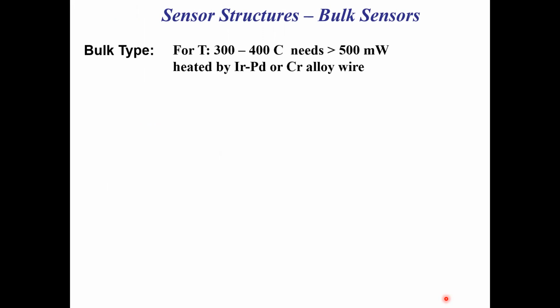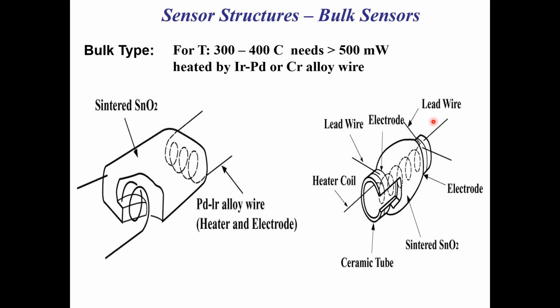So if you make a bulk type sensor, which you can, it requires a lot of power. If you want to take a bulk type sensor and heat it up to 300 or 400 degrees C, where the sensors are active, you need large power, heated by iridium, palladium, or chromium alloy type wire. You can see the bulk type design of sintered tin dioxide sensor heated with palladium iridium wire, and the other palladium iridium wire can be used to detect the change in resistance of the material.